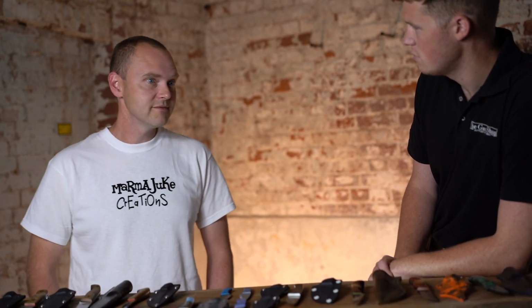The 61 can be a bit brittle, and what you'll get is edge chipping at that if you abuse it. Everything's all down to how much you abuse them. 59 is probably a good benchmark for a hunting knife. Most cheaper end production knives are generally softer, so they handle a bit more abuse. So they'll be probably 57, 58, and I've seen reports of them being down to like 55 HRC, which means you can sharpen them really easy because it's soft steel, but it won't hold the edge.